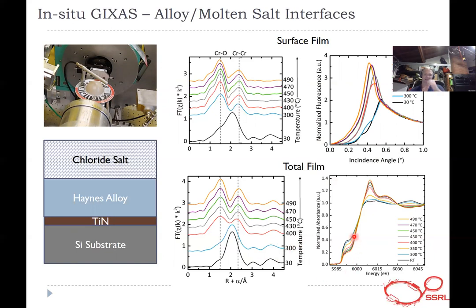And you can see that here at the chromium edge, we go from an FCC chromium. The chromium is an alloy constituent of the Haynes alloy. It goes from an FCC chromium constituent to an oxidic chromium species with temperature as it's leached out. And that is a lot of information about the corrosion pathways in that system.